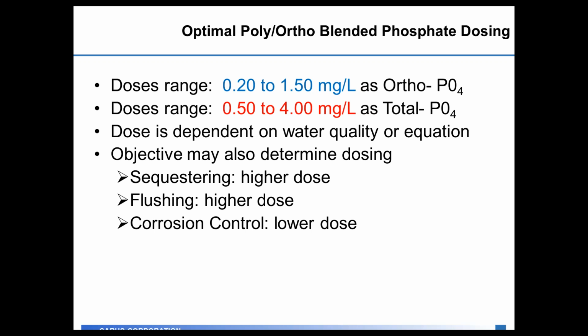So, optimal poly-ortho blended phosphate dosing. The dosage can have a range here as well, from as little as 0.2 to 1.5 milligrams per liter as orthophosphate, and then a total phosphate dosage of a half a part to 4 milligrams per liter. The difference between the ortho and the total number is how much polyphosphate you would have in the system. You can't measure polyphosphate directly, but by measuring the total phosphate and the ortho, you can get at it as the difference between those two.